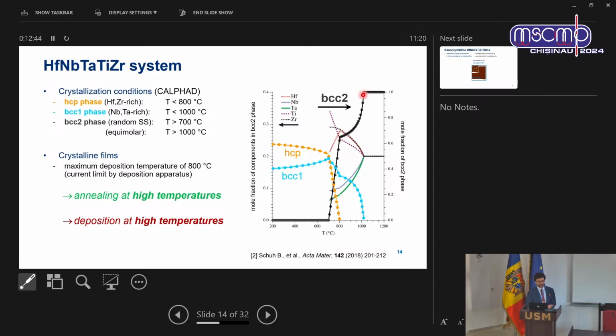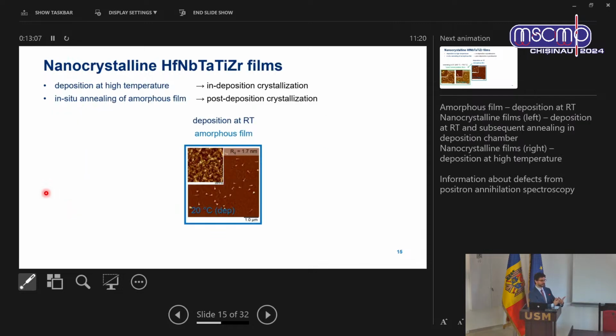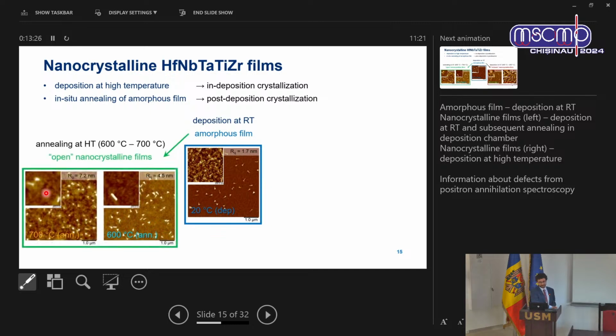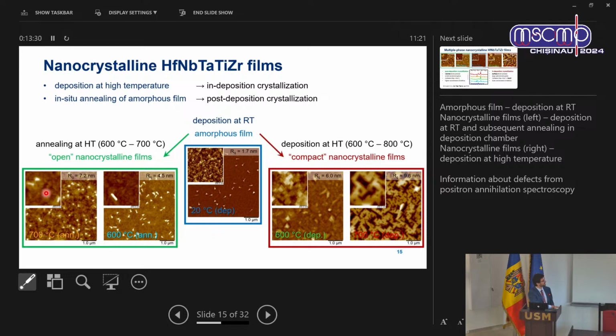And that was a problem for our laboratory because the current maximum deposition temperature limit is up to 800. So we were in the intermetallic region. But still, we had two ways how to introduce temperature into our system, and we could do that either by increasing the deposition temperature and crystallize the films during the deposition, or to deposit amorphous film and then heat it up and recrystallize it after the deposition. And here you can see the resulting structures of the annealing and of the deposition at high temperatures. I think you can clearly see that both ways went to production of crystalline films. However, the more effective one is the red one, when we deposit immediately at a heated substrate.